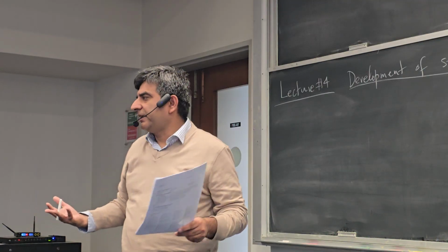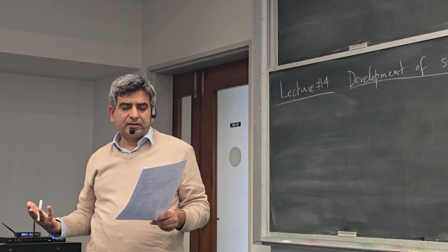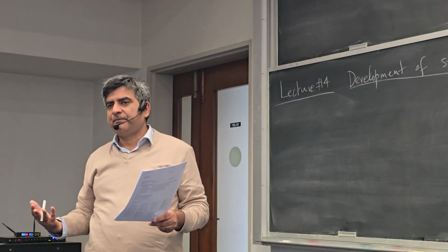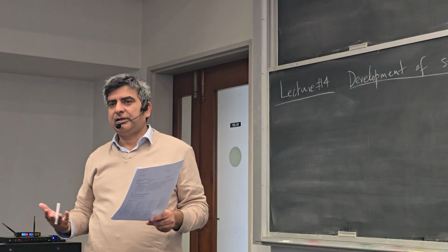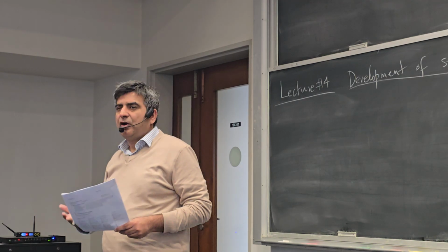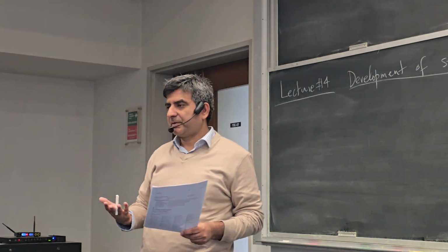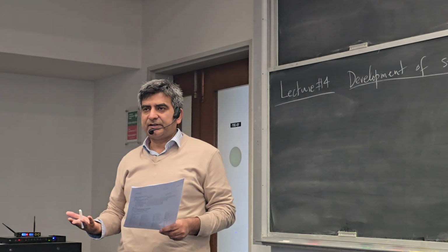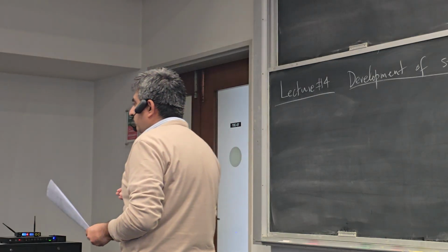For example, triclinic just has either a 1 or a 1 bar. Monoclinic has a single 2-fold axis, a single mirror plane, or a two-fold axis and a perpendicular mirror plane. Orthorhombic has at least two two-fold axes of rotation that are mutually perpendicular, or two mirror planes that are mutually perpendicular. Tetragonal necessarily has a four-fold, 4 or a 4-bar axis.